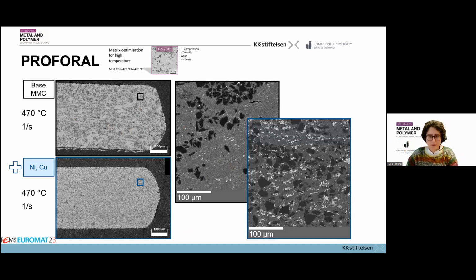If we look into the material reinforced with these nickel-based phases, you see already from a macro scale down here that you cannot perceive the same kind of deformation that we had above. So the nickel phases somehow are interlocking, and you see it here, interlocking with the silicon carbides and make the whole microstructure much stiffer than before, and it can withstand the compression stresses more efficiently than the base material. So that resulted in that much higher peak stress, and we can see in the microstructure also what is happening.